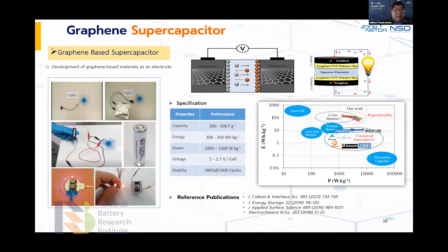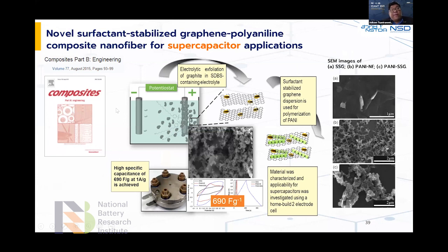This shows some of the devices where we put it into the form of a cylinder cell and also a pouch cell. I will show you some examples of how to mix the graphene with the nanocomposite. For example, we put graphene composite with polyaniline using a special surfactant for stabilization, and we use graphene synthesized by electrolytic exfoliation, and we can reach about 690 farad per gram. It's quite impressive. It's quite high because it's the combination of the EDLC and also the pseudo-capacitance effects.